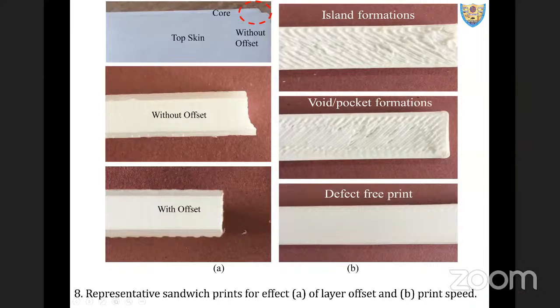Then depending on the printing speed, this is how the samples show defects at different printing speeds. At a suitable printing speed, you will get a perfect sample without pockets, without islands, without scrubbing of your nozzle into the system which is being made. So we need to look at all these parameters when we are really looking at different material systems.